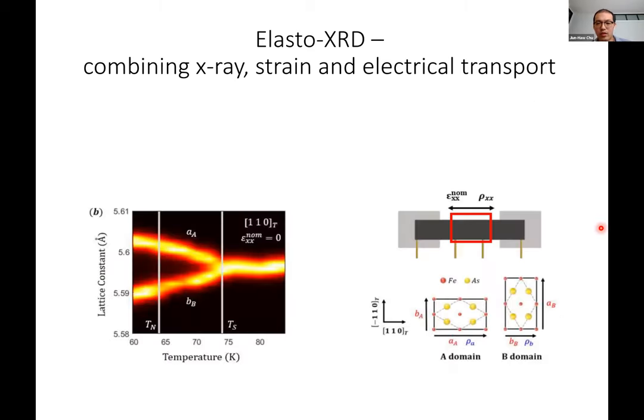so a typical measurement like this, now we have a matched set of samples mounted across the two sample plates, and then we are measuring transport simultaneously. And then using a grazing angle, we can actually measure a large portion, basically the area of the samples where we're performing the voltage measurements. So let's say we're measuring under those samples, and then below the structural phase transition, you'll form structural domains with some domains aligning this way and some domains aligning the other way.